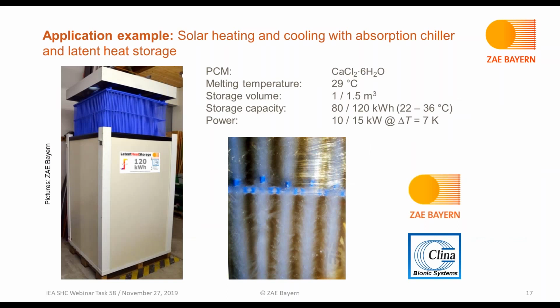On this slide, you see a picture of the storage that has been used in the installation. As I said, the PCM is calcium chloride hexahydrate with a melting temperature of 29 degrees C. There are two types of storages, one with 1 and one with 1.5 cubic meter storage volume. And as you can read, the capacity is either 80 or 120 kilowatt hours in the temperature range between 22 to 36 degrees C.